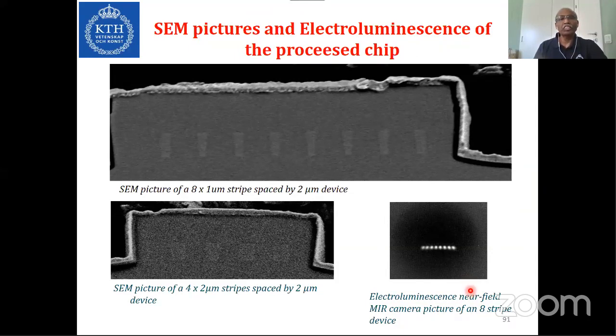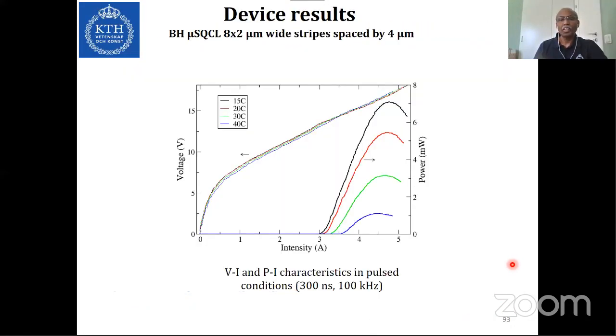This is the same picture and the electroluminescence of the processed chip. For example, here, the electroluminescence of 8 stripe devices, and some of the device results. You see, when I told you that it can go up to several tens of volts, here it can go to 15 volts, and the pumping current is 3 amperes, but these are not at all the magnitudes of the telecom lasers.